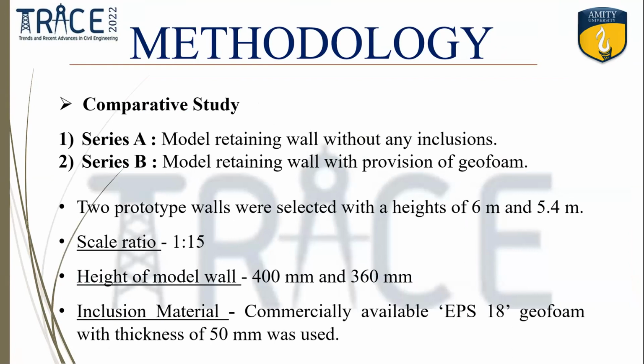I have conducted two series. Series A is the model retaining wall without any inclusion. Series B is the model retaining wall with provision of geofoam material. The experiment set of this study is identical, with only the difference of provision of geofoam material. Two prototype walls were selected with heights of 6 meter and 5.4 meter. According to the test availability criteria and the scale ratio, the height of the model wall is 400 mm and 360 mm.